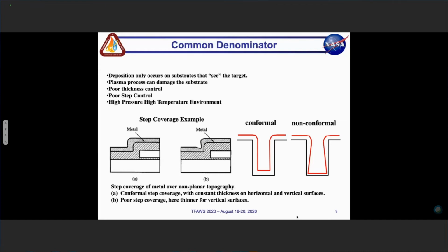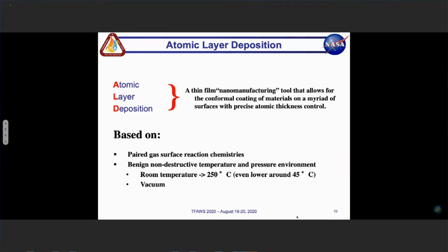If you have something like a trench, or which has grooves and divots inside of the surface, what you end up seeing is something that doesn't completely cover that particular structure beautifully. What you end up having is material which is not uniform. So you have thinner walls, thicker walls, and that can lead to issues when you're dealing with high aspect ratio geometries.